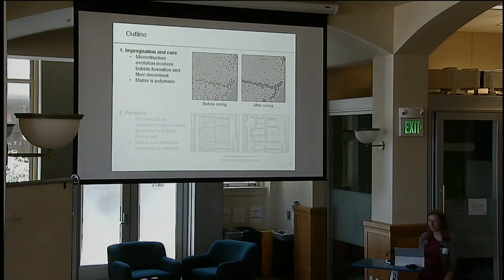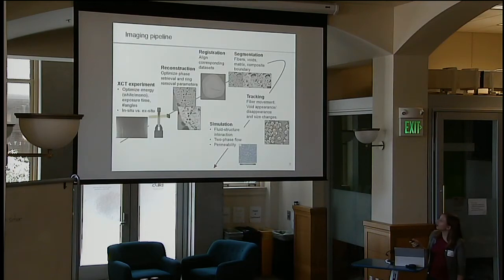So we'll start off with impregnation and curing. The overall imaging pipeline is shown here on this line that you can follow. The first step in the imaging pipeline just starts with the experiment. Here we need to optimize the imaging parameters, including the energy that we use, the exposure time, and the number of angles, to give us the best images for the later steps of segmentation, tracking, and simulation.